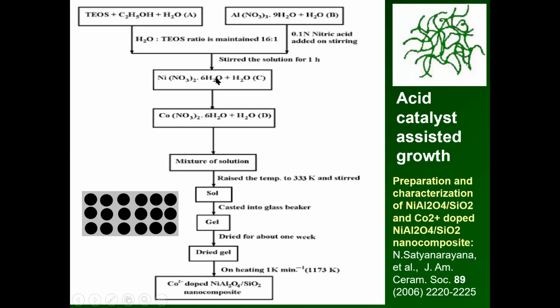We characterize at every stage; we monitor through XRD, FTIR and DSC. At that time we did not have a DSC or TGDTA, but we could do XRD and FTIR. In fact, this experiment made us buy a TGDTA because it is very essential for monitoring this synthesis process. Once it is dried, you do controlled heating. When you do the controlled heating, you get nickel aluminate nanoparticles dispersed in SiO2. These black spheres are nickel aluminate or cobalt nickel aluminate, and the gray background is SiO2. This is a schematic, but how do we know that this can occur and how do we monitor it? We will see the next one.